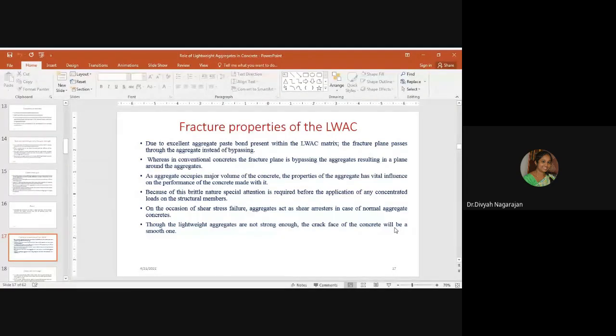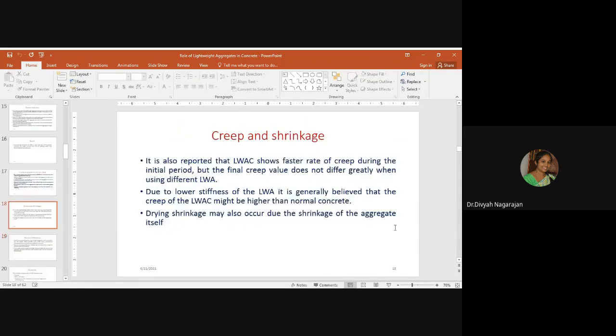On occasion of shear stress failure, aggregates act as shear arresters in the case of normal aggregate concrete. But as the lightweight aggregates are not strong enough, the crack face of the concrete will be a smooth one. Creep and shrinkage. Coming to long-term effects of lightweight aggregate concrete, it is reported that lightweight aggregate concrete shows a faster rate of creep during the initial period. But the final creep value does not differ greatly when using different lightweight aggregates manufactured from various places.